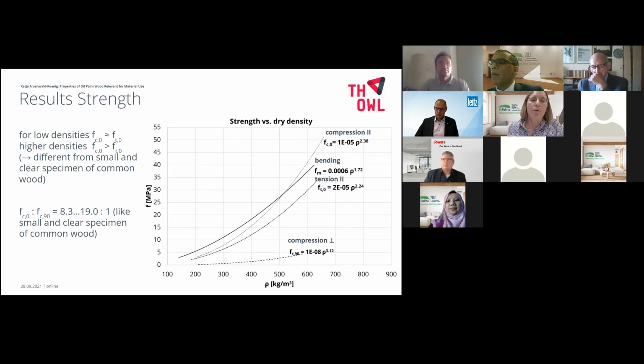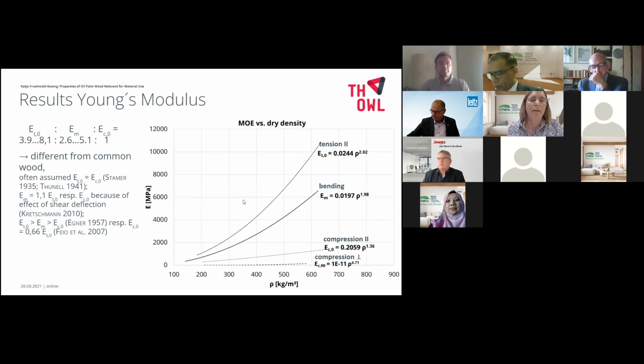Compression, bending, and tensile strengths increase with density. With increasing density, compression strength is above bending and tension strength. This is different from common wood species. Next slide. In contrast to common wood species, the tensile Young's modulus is above the bending MOE, and above the Young's modulus in compression. Next slide.